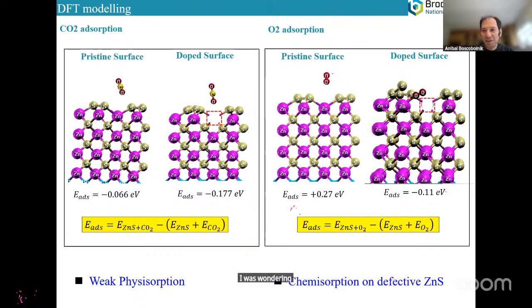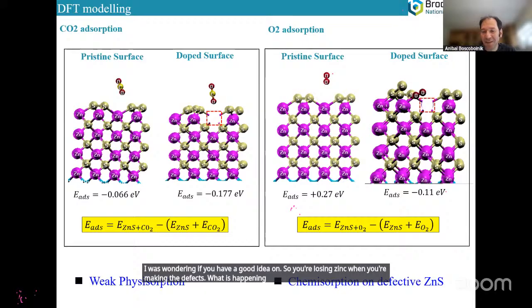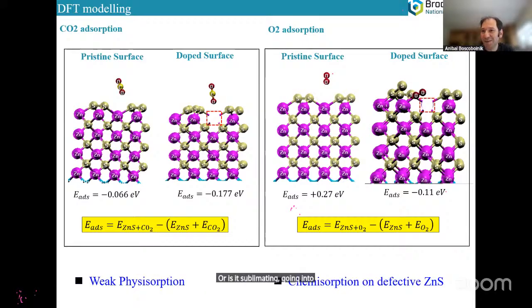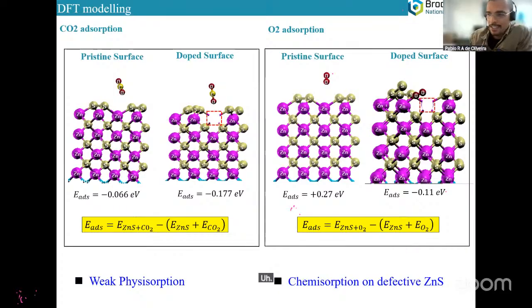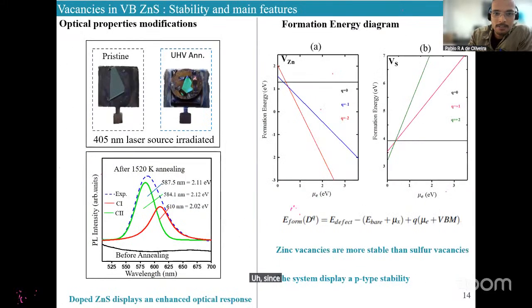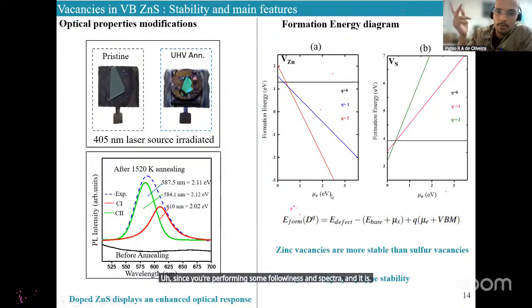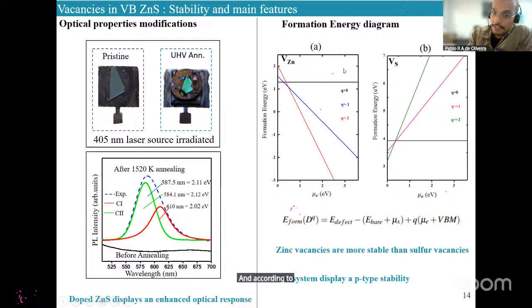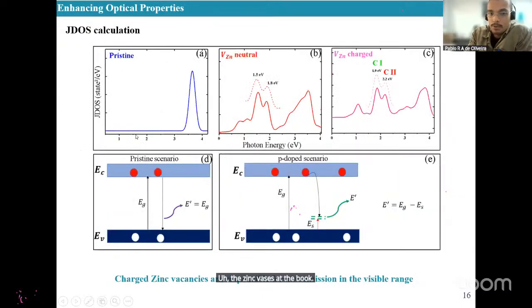So I was wondering if you have a good idea on, so you're losing zinc when you're making the defects. What is happening to that zinc? Or is it sublimating, going into the bulk? Do you know? At first glance, I would say it goes away all the way out and sublimates, because the bulk seems to be still zinc deficient, since you performed some photoluminescence spectra, and it is most likely bulk sensitive. And according to the DFT calculation to support these experimental results, the zinc vacancies in the bulk are the most stable ones. So I would say the zinc is most likely sublimating as another species. Okay.